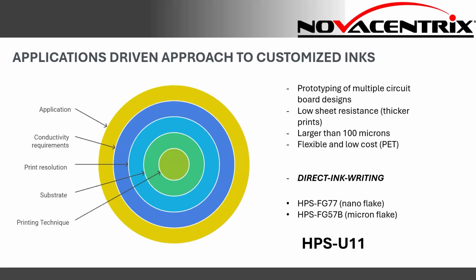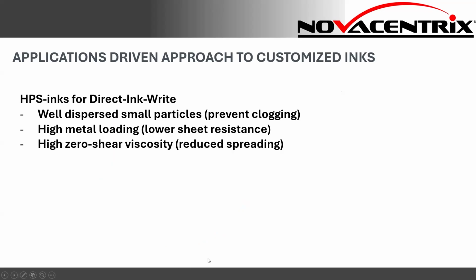So HPS stands for high performance silver. The U is for our new family of inks, the Ultra family. So what are some of the changes that we think about when we are trying to design an ink that is specifically for direct ink writing? If you think about a dispensing process, first of all, your inks have to be well dispersed with small particles so that you can use smaller and smaller nozzles without them getting clogged. You need to have a very high metal loading, and that is because a high metal loading usually, not always, but usually, will correlate to lower sheet resistance. But you also need high zero shear viscosity, so that when you actually print it, there is less spreading.